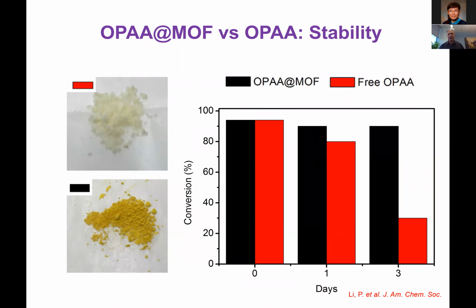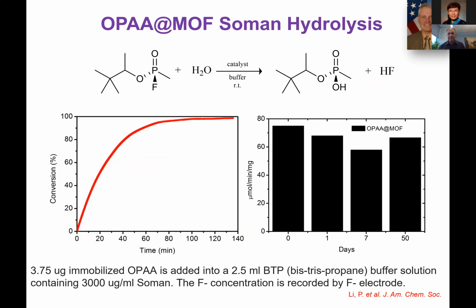More importantly, the DOD wants to know how these materials behave in the solid state. If you take the enzyme itself and lyophilize it versus our composite, filter it, put it at room temperature, and every day measure the catalysis, I don't have day 4 here, but day 4 showed that our composite did not get affected versus the free enzyme is completely dead. So besides we could get the same reactivity if you wait 30 minutes, we stabilized it drastically.